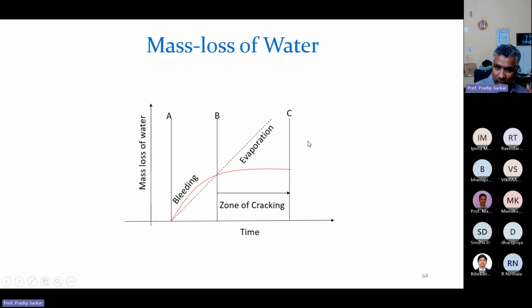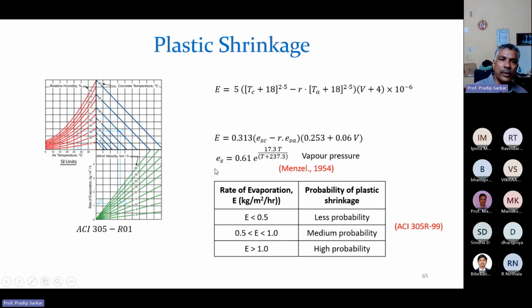So for this we have some nomographs in the American ACI code, the American Concrete Institute's ACI 305, where the evaporation is related to the concrete temperature, R the relative humidity, TA the atmospheric temperature, and wind velocity. All these parameters, the concrete temperature, relative humidity, atmospheric temperature and wind velocity, are measurable using sensors. So if we can fix those sensors and get the data, then using this relationship we can find out what the evaporation rate is.